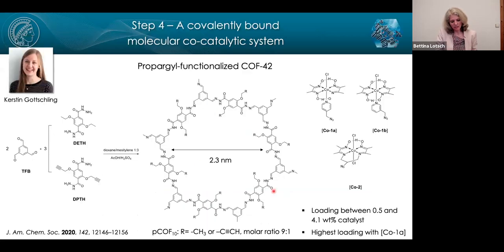And so we developed a system based on COF-42, where we functionalized a cobaloxime co-catalyst with an azide group, and then we clicked this azide functionalized co-catalyst to a propargyl functionalized COF-42. And so that actually gives loadings that are not ultra high, so a couple of weight %. But as you'll see, this is actually quite the right ballpark to actually achieve good catalytic activities.